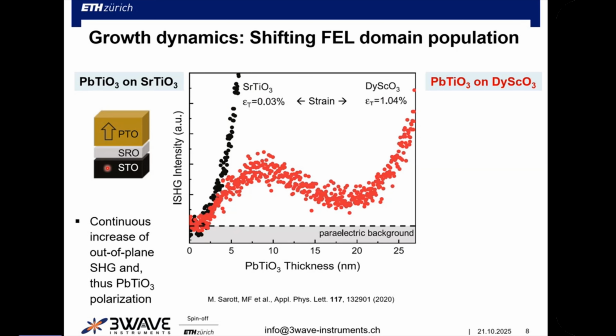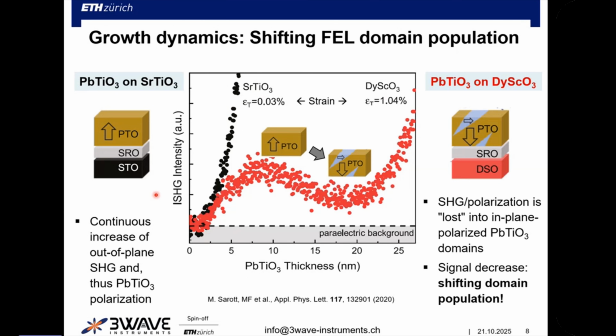So this black curve. The red curve, it starts the same way. So you get out-of-plane polarized lead titanate. At some point that gets unstable and you flip the polarization into the plane. So it's lost for this signal contribution. And it's not that from a certain point onwards you grow in plane. You really have flips from out of plane to in plane. This is why you lose signal here, and it does not just stay stable. And after a while, this stabilizes into a multi-domain pattern that then simply increases again in thickness, and that's when you have your other rise again.